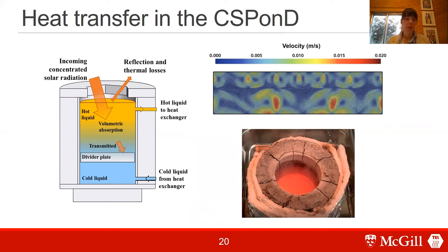Particularly because of the unique way of heating the salt, we have flow driven by temperature gradients. And we have very hot salts that have some unique properties. So thermal radiation is actually very important. And because of this, a lot of the standard heat transfer correlations are not applicable in these contexts. And so it leads to a lot of issues in terms of predicting thermal behavior.